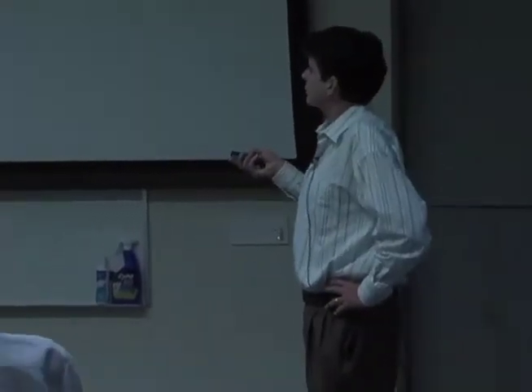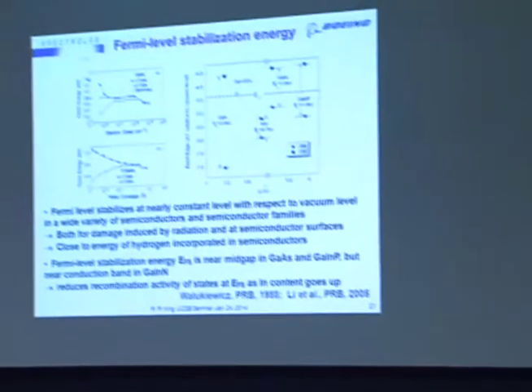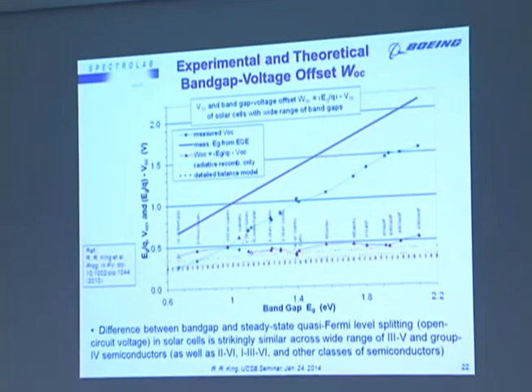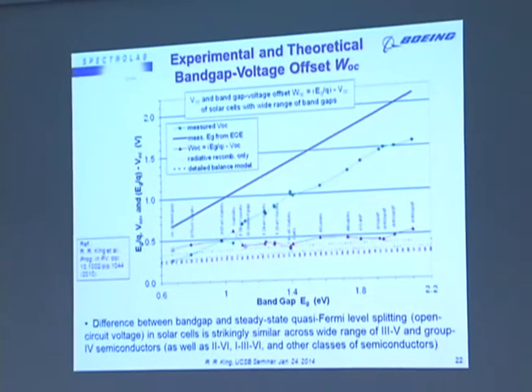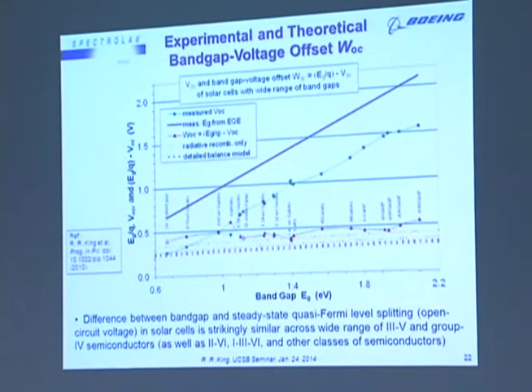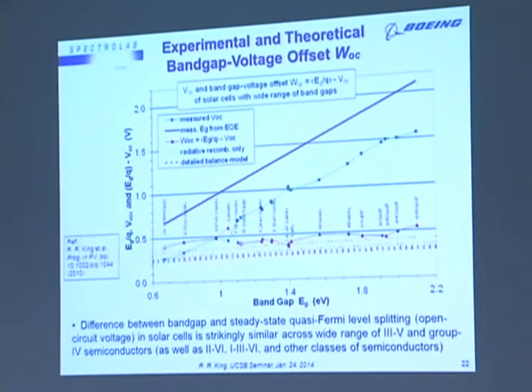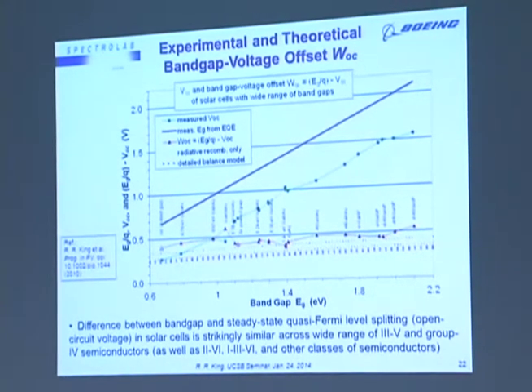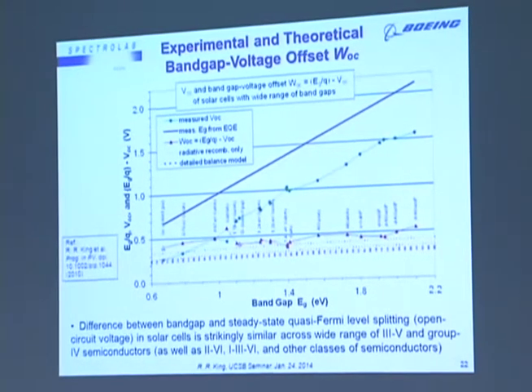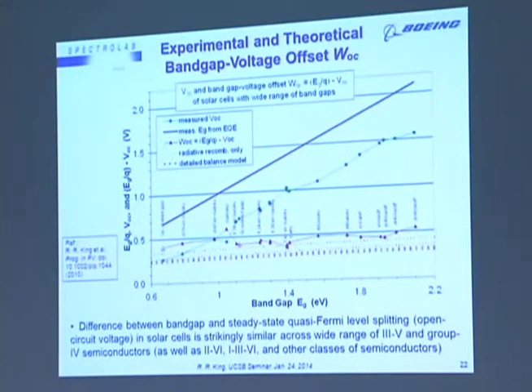So a little bit different flavor of common themes among different semiconductors, but one that still shows the tendency for materials to have a constant behavior even among different semiconductor compositions and families, is this concept of a bandgap voltage offset, or W_oc. An observation that many of us have made is that if one plots the open circuit voltage for semiconductors for a wide range of compositions and band gaps, the difference between those two, the band gap voltage minus the open circuit voltage, turns out to be very constant among lots of different types of semiconductors, spanning this whole range of useful band gaps for making multi-junction cells.